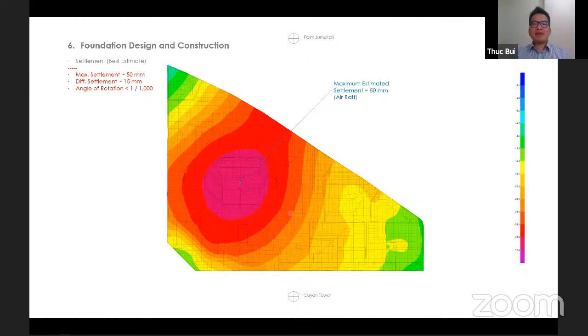The estimated foundation settlement is about 50 millimeters at the center of the core, with maximum differential settlement of around 15 millimeters, and the angle of rotation less than 1/1000. So everything is good.